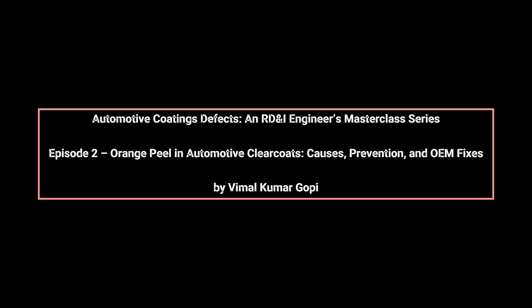Viscosity control, both at low shear during flow and under high shear during spraying, is essential. Kinematic and dynamic viscosities must be tuned to ensure proper atomization and wet film leveling. Modern RD&I practices often include real-time viscosity monitoring and spray testing to confirm that the coating maintains the correct shear-dependent flow characteristics throughout the application window. Minor deviations in viscosity caused by temperature shifts or improper mixing can push a marginal formulation into visible orange peel territory.